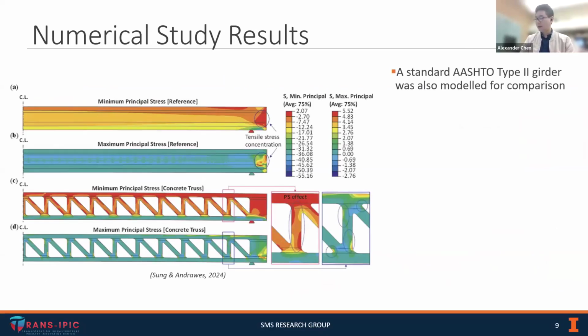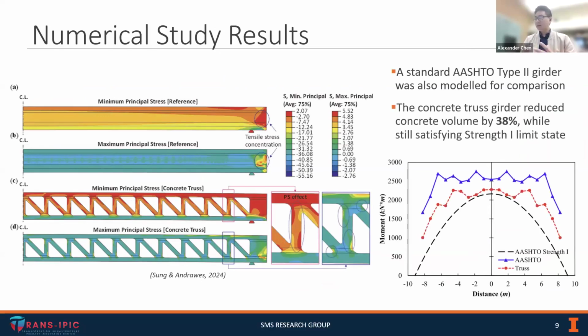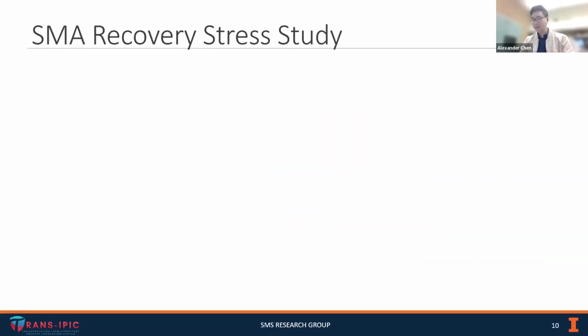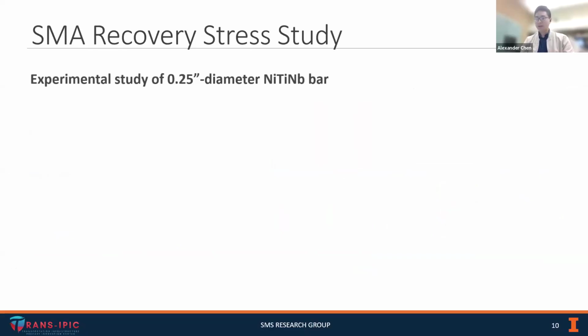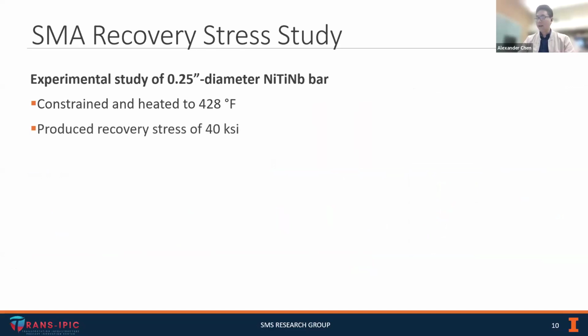The performance of this girder was compared against a standard AASHTO Type 2, and what we found was that the concrete truss can reduce the volume of concrete by 38% while still meeting the limits to satisfy a Strength 1 limit state. So these are very promising results, and our next step was to validate it experimentally. To do so, our research group studied the recovery stress of a 1/4-inch diameter nickel titanium niobium bar. This was done by constraining the bar and heating it up to 428 degrees Fahrenheit, and that caused it to produce a recovery stress of 40 ksi.